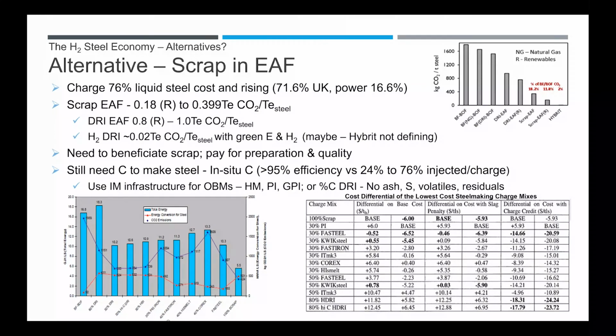So an alternative is scrap in the EAF. If we can clean up the scrap, currently we can get 0.18 to 0.4 tons of CO2 per ton of steel, depending on whether it's renewable energy or not. But we need to beneficiate the scrap. We need to have a mentality change to pay for preparation and the quality, both at the scrap dealers and in the steel industry. And we need to still have carbon. In situ carbon is much more efficient in terms of reactions and performance. So we need to find some mechanism to import some good efficient carbon to the furnaces, and possibly continue to use the DRI, the hot metal, pig iron and granulated pig iron, and save the infrastructure of the OEMs. And of course, DRI is an option, but preferably with carbon, because it has no sulfur, no ash, no volatiles, and no residuals. Next, please.